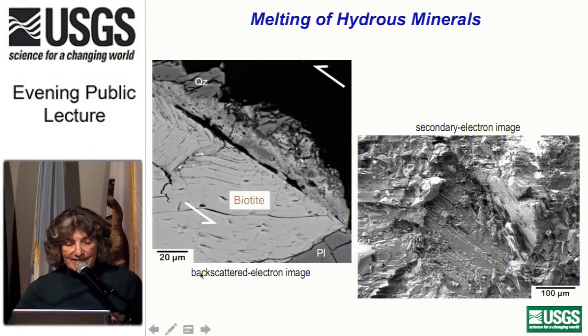Over here, this is the last of our backscattered images. So this was the sawcut surface again, and this one has a biotite crystal that was right along the sawcut. Biotite's a hydrous mineral. It has water in its crystal structure. These hydrous minerals melt at relatively low temperatures, about 700 degrees centigrade. When it melted, it not only generated perhaps a water-rich melt, but it seems to have also separated out a vapor phase, all that water that was melting too.